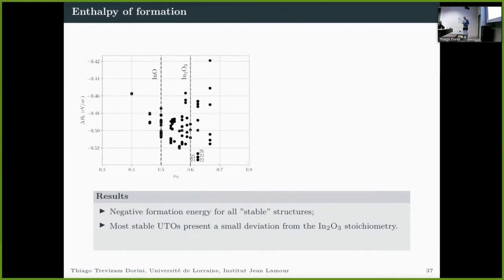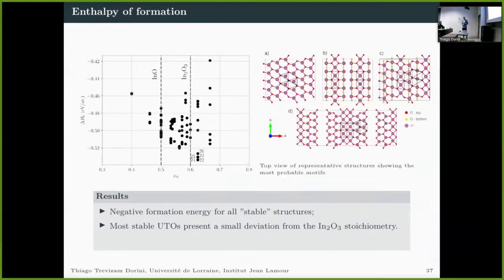The most negative ones present a composition that is a bit deviated from the ideal In2O3. And from this, you can start to see what are the typical configurations that we see on these oxides. First, I've separated into 4 structures. The first one, we have formation of hexagons on the oxygen sublattice.